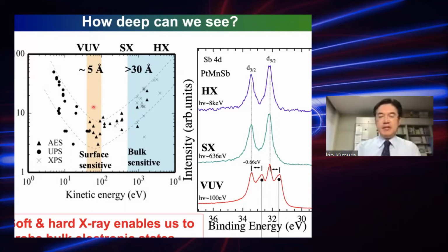But I'd like to mention that there is a serious problem, which is a short penetration depth. In other words, surface sensitivity. Using conventional photoemission spectroscopy with ultraviolet or soft X-ray radiation, the kinetic energy of a photoelectron is as small as 100 or 1,000 electron volts, which enables us to observe only the very surface region. The penetration depth is as small as 10 angstrom. So in order to get the true bulk electronic structure, you need to use higher photon energy, let's say hard X-ray.